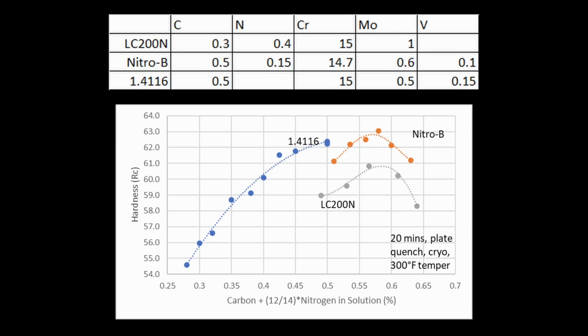That's very interesting. Yeah, well, the chromium in solution is still part of it. I mean, Nitro-B gets to 63, not 64, 65. But the Nitro-B might have similar corrosion resistance to LC200N because it's got the same chrome and moly in solution. Now, it has more carbon, which can have some complicating effects versus LC200N, but it's definitely an interesting test that could be done. Because the matrix composition, the chrome and moly in solution, is the same, but it gets a couple points harder. So the Nitro-B would be an interesting one to look at in terms of corrosion resistance. So one of these days I might do a side-by-side salt spray test between the two steels. I think it would be very interesting.